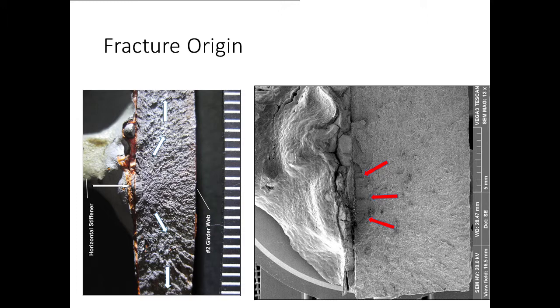We cut the specimen down and stuck it in a scanning electron microscope. In this particular area here, these particular fractures were cleavage fractures indicative of brittle failure. But we have this thumbnail area of interest, and you can see they've got some horizontal lines across there, and these are termed ratcheting marks, and they're a sign of fatigue. And when we amped up the magnification of this to about 1,000, we were able to detect fatigue striations. So this little thumbnail is our critical sized fatigue crack that caused the brittle fracture. It was about 4 millimeters long and about 1.5 millimeters deep.